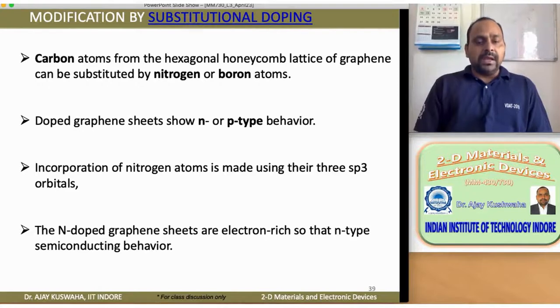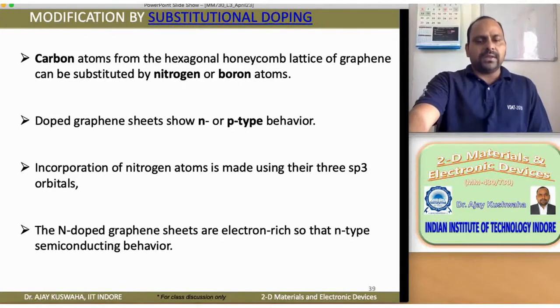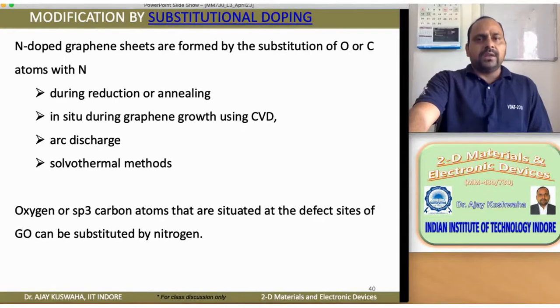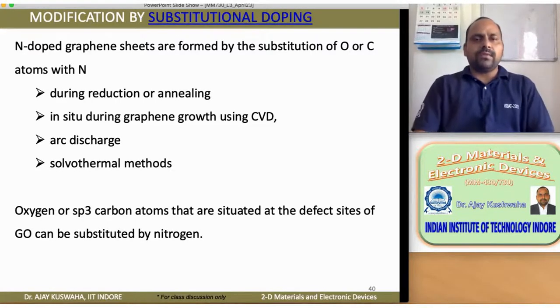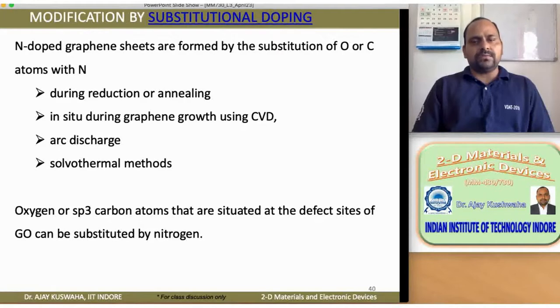And if we are attaching nitrogen, then we are going to create N-type graphene, and it will be an electron-rich system. This N-type doped graphene, basically nitrogen-doped graphene, is extensively studied. There are a number of reports you can see, and it shows N-doped graphene sheets are formed by the substitution of oxygen or carbon atoms with nitrogen. If there is pure graphene, then carbon, and if it's graphene oxide, then of course oxygen will be replaced. It can be achieved during reduction or annealing, in situ during the growth of graphene in the CVD process, where you can supply some amount of nitrogen, or by arc discharge or solvothermal method.